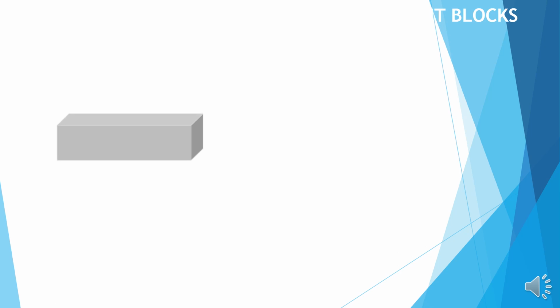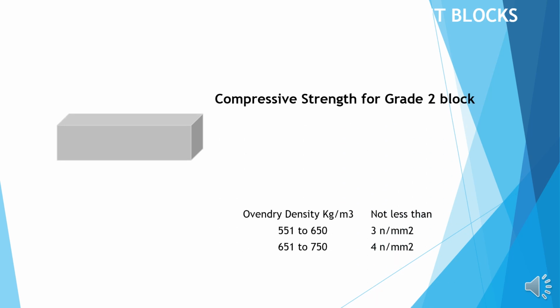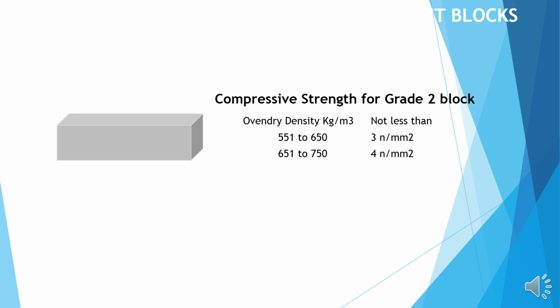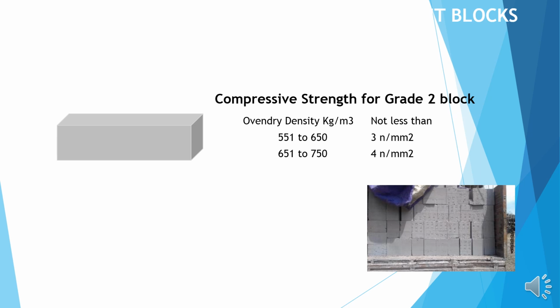AAC blocks. Compressive strength for a grade 2 block. Ovendry density 551 to 650 kg per m3 will be 3 newton per millimeter square. 651 to 750 kg per m3 will be 4 newton per millimeter square. Relevant code IS 2185 Part 3 Class 4 Table 1.